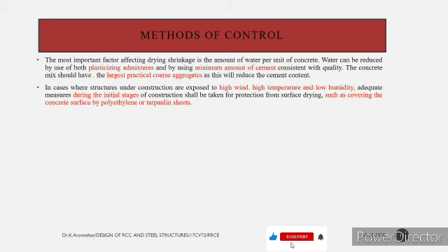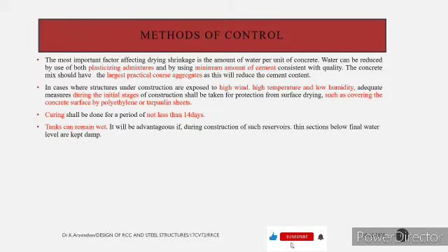During the initial stage of a water tank, while fabricating the concrete, and in those 28 days, if there is a high wind or higher temperature and low humidity, what happens? The water in the concrete gets evaporated. So during these initial stages, what you can do is cover the concrete surface using polythene or tarpaulin sheets. In a water retaining structure, curing is essential for 14 days as per the guideline.